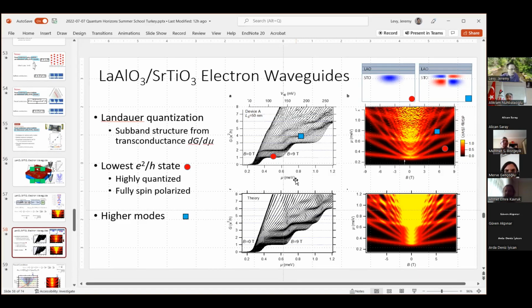Yes. Okay, I see another question. When you apply strain, you spontaneously lose superconductivity. When you remove it, the system turns back to the superconducting state. How fast is this transition? That's a good question. There is a limit to the speed with which we can change the strain state. It turns out that there are piezoelectric transducers that we have to energize, and when they energize, they heat up. So if we try to change it too rapidly, the whole system warms up. And so we are not able to quickly change the strain state.